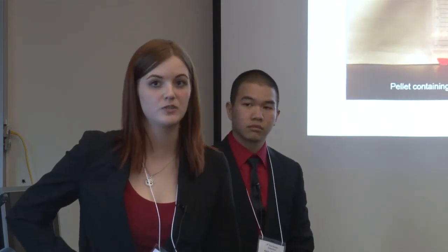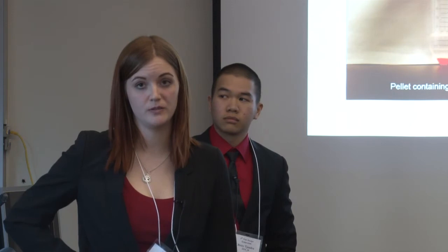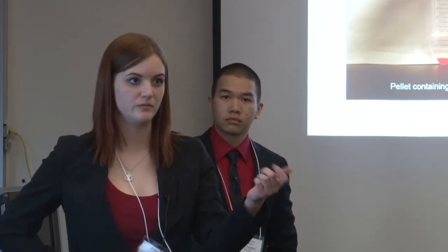But it is a kinetic process. Over time, you would sort of detach, and some of it would end up in the water. Do you know the half-life of the bound dye? I'm not sure, but one thing we did was calcinate the particles after we had dyed them. If we just had the dye as a powder with the mesoporous particles in a crucible, and put it in the oven at 600 degrees for 12 hours like we did for the calcinating step, it would be white afterwards because all the dye would burn off. But we did calcinate it with the dye, and it doesn't stay red, but it does continue to retain color, which makes us pretty confident that the dye is firmly attached onto the surface.